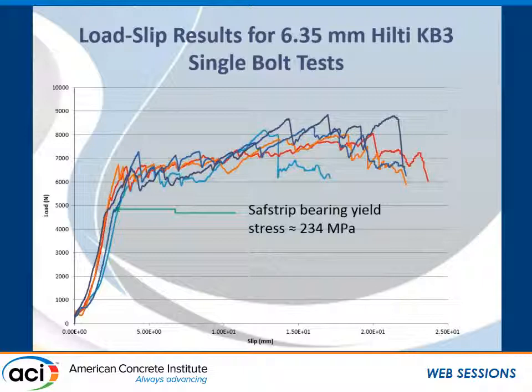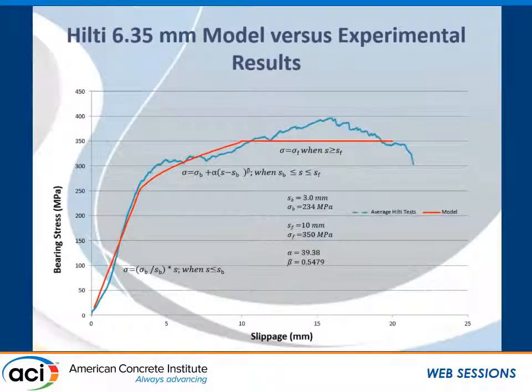In the interest of brevity, I am going to concentrate on the model we developed for the 6.35 millimeter Hilti KB3 anchor bolts that we took a look at. And in developing our bearing slip model, we took the representative experimental data curve and modeled it in 3 sections. The first section of the curve was best fitted with a straight line up to our bearing yield point, and the bearing yield strength of the FRP is achieved at a corresponding slippage of about 3 millimeters. That bearing yield strength was 234 megapascals.